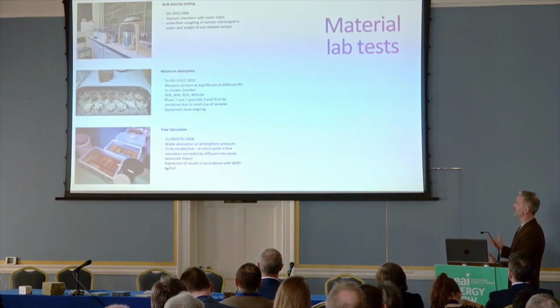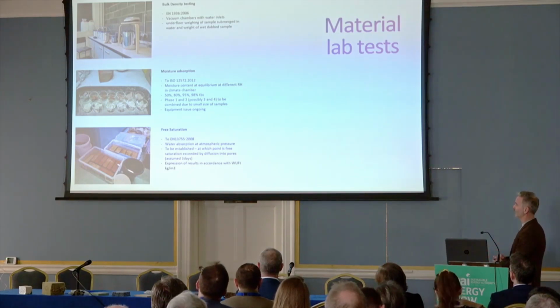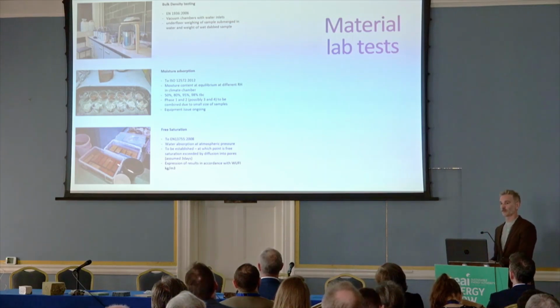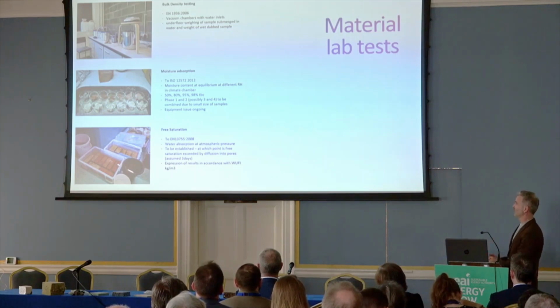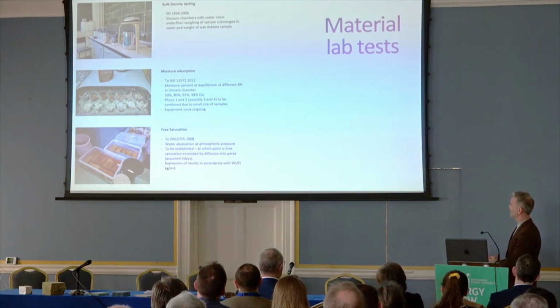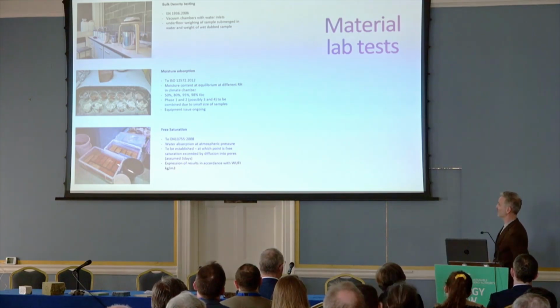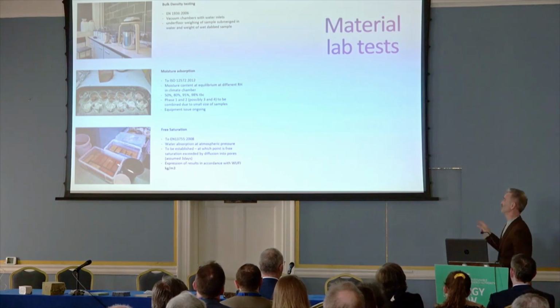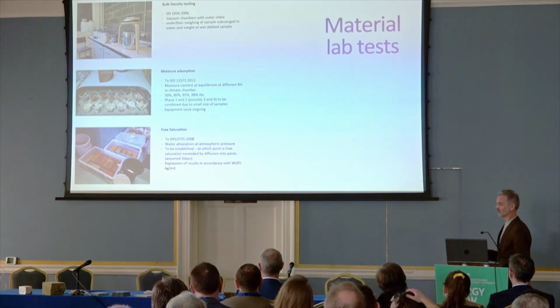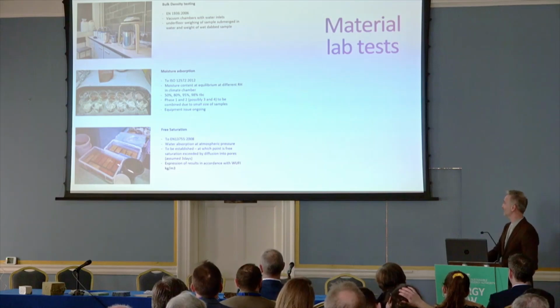Bulk density testing allows us to get the density of the material, but also the porosity of the material, which affects many of the other parameters. Moisture adsorption is the uptake of moisture vapor, and we're testing that at a number of different relative humidities. At the moment, the big investments we've made in two big multi-thousand-euro climate chambers are both causing us problems, so this test is stalled. That's why we're presenting an incomplete data set today: it's a hardware issue that we have.